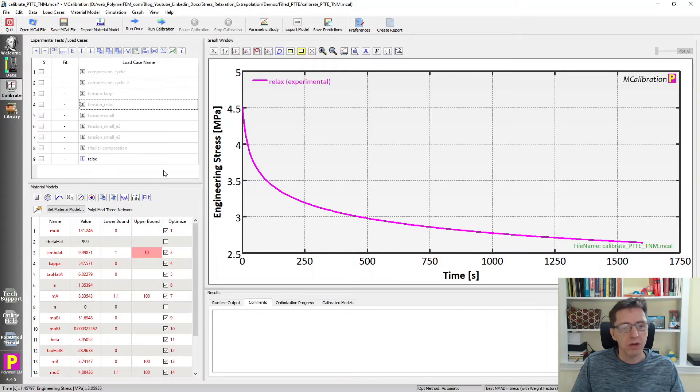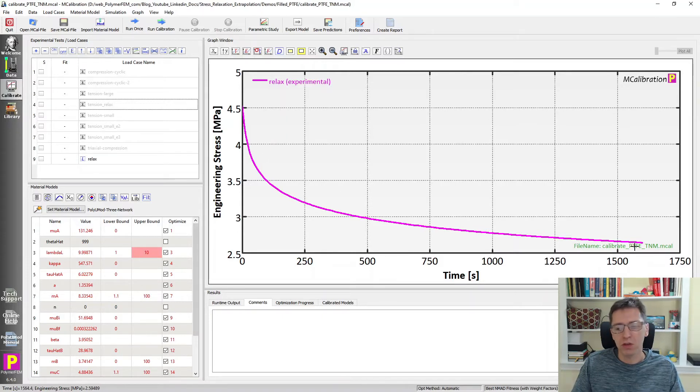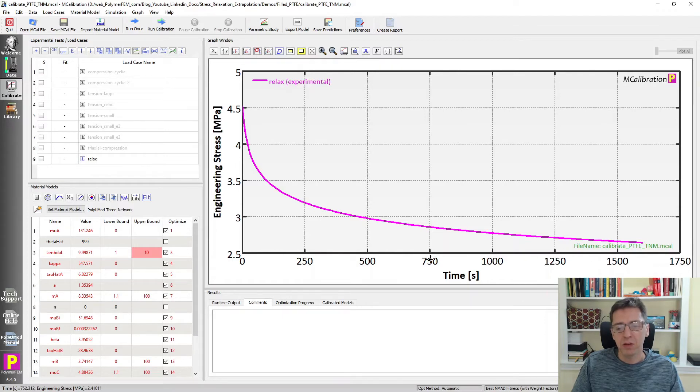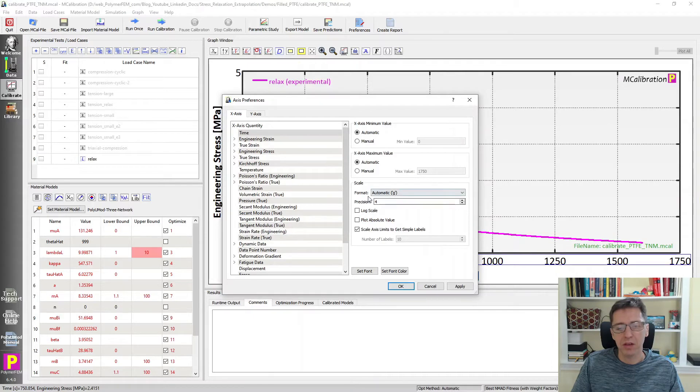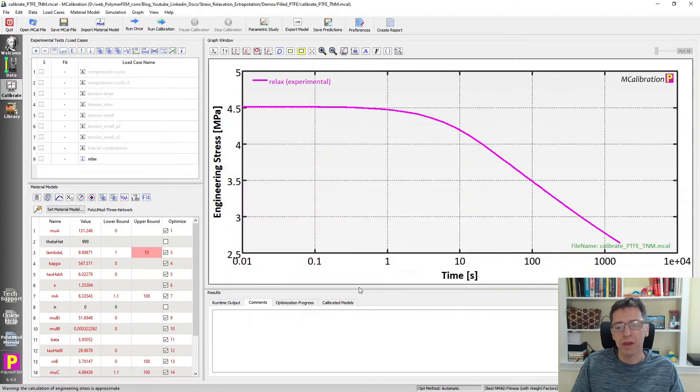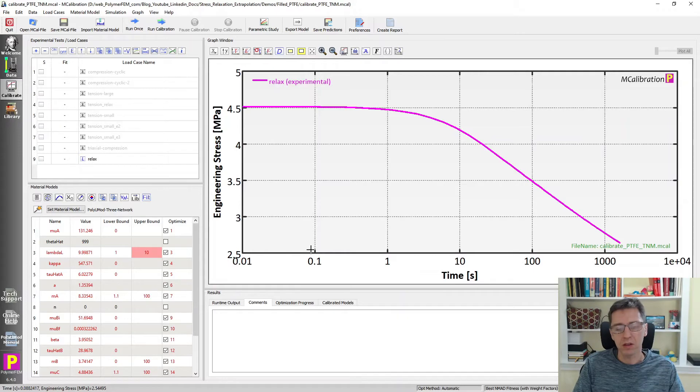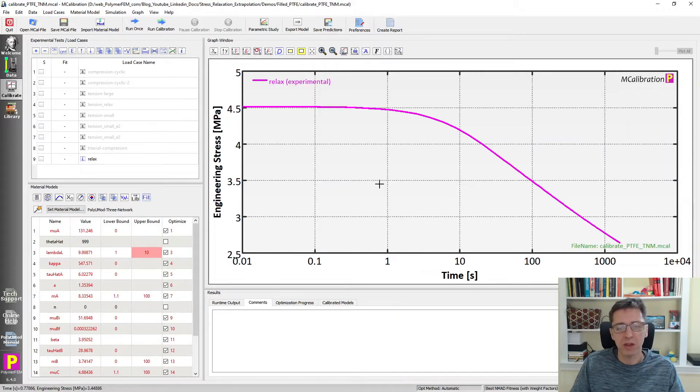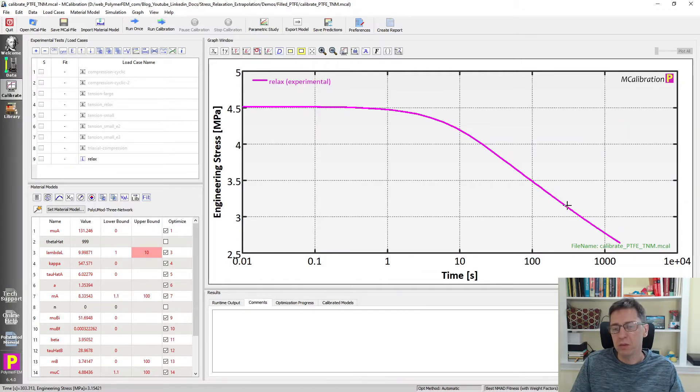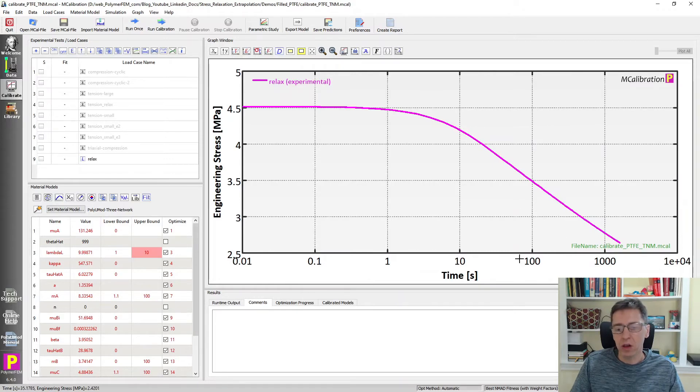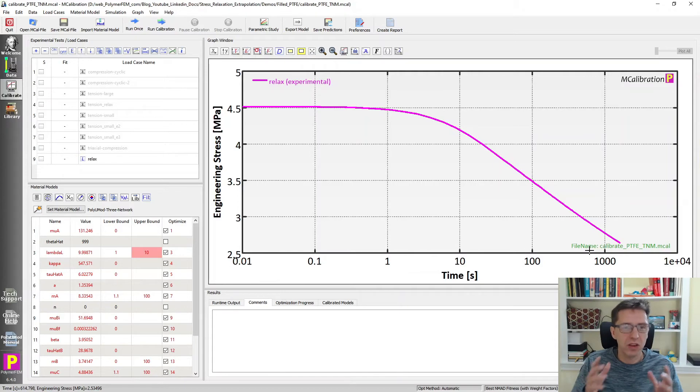One of the things you should be aware of is when you plot time versus stress like this, it's hard to see what's going on unless you switch over to plot logarithmic time. So I'm double clicking on this axis, setting it to log scale. This is what the data looks like in this case, and this is very typical for thermoplastic materials of this kind. The stress decreases in magnitude almost linear on the log scale when time is on the log scale. That is the traditional way you see.